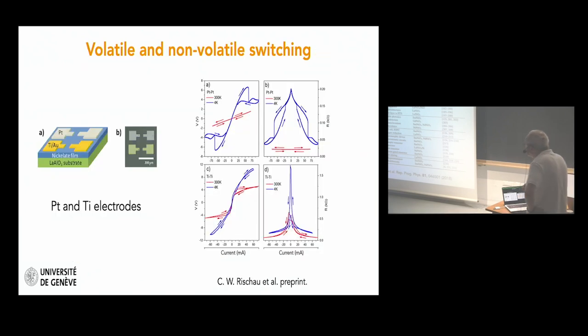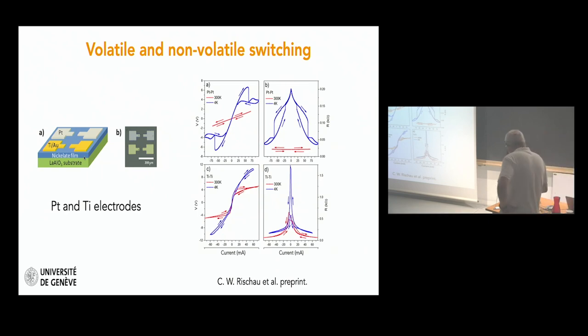And I wanted to mention that recently in Geneva, we used a nickelate film. You see here the device. This is a substrate, lanthanum aluminate, and a nickelate film. Depending on the choice you make for the electrodes, you can get volatile or non-volatile resistive switching on the same platform. And this could eventually be an interesting system to pursue for possible applications.